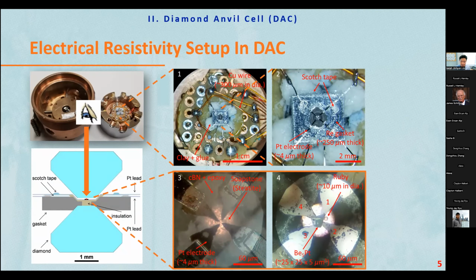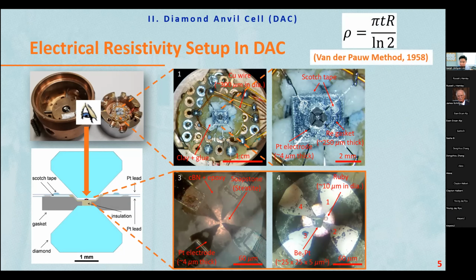We use a platinum electrode. It is the best for electrical resistivity under pressure. And nicely put the sample at the center and then ruby beside. So this is the best setup so far. This is one of my best setups for the electrical resistivity of platinum beryllium 5. And we use the van der Pauw geometry to estimate resistivity out of resistance,